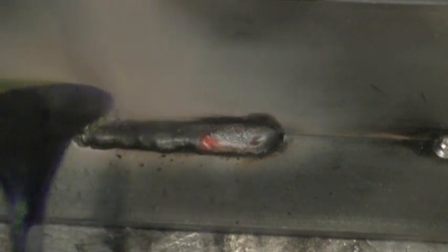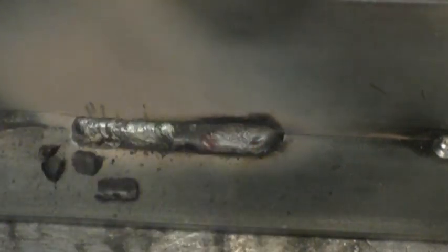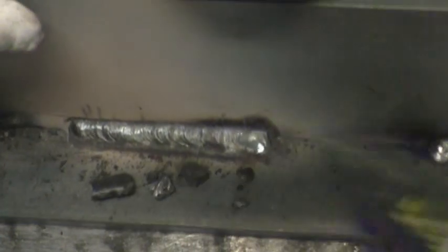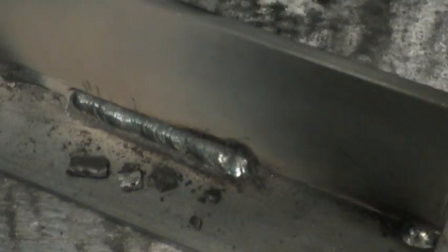The slag will get in the root of the weld in the corner, and it will prevent you from penetrating into the corner. And again, you can check out the video on fillet break tests and get an idea for what I mean by that. Okay, but I've actually got a hollow spot at the tip of this. I'll get my flashlight. And I can see where the weld is not. Let me brush this off. I can see where that weld is actually not in the corner.